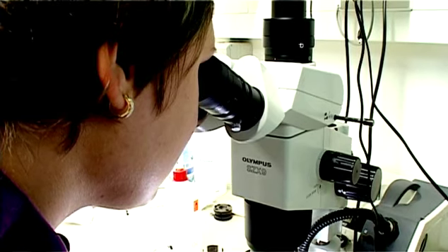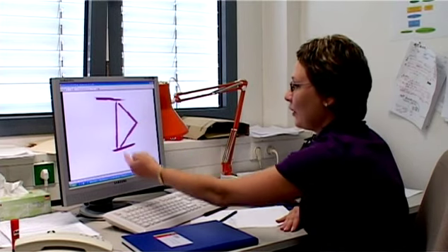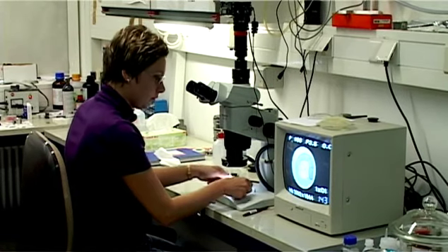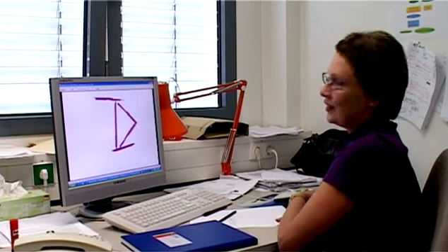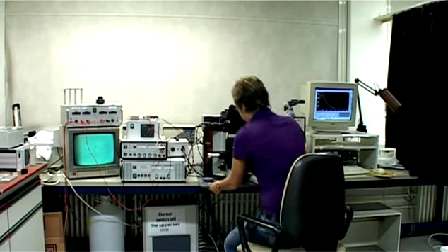We got a new phase of boron. It's semiconductor, it's not superconducting, but it's quite hard material, second elemental material after diamond, which has such high hardness. And recently we managed in synthesis of single crystals of high pressure, high temperature phase of boron. As you can see, this is quite long crystals, it's 25 microns. Now we are preparing for our experiments at ESRF using synchrotron radiation for investigation of that phase.